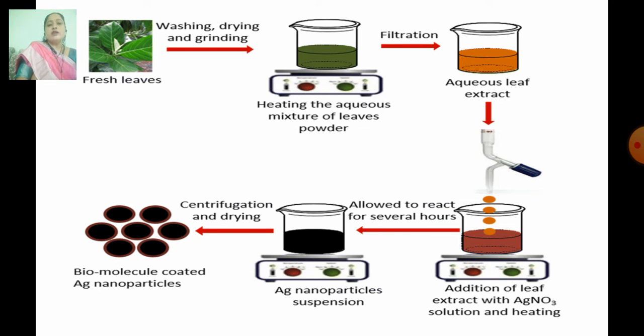After the formation of silver nanoparticles, you have to centrifuge it. After centrifugation and drying, we get biomolecule coated silver nanoparticles, and these silver nanoparticles have a number of applications in the medicinal field and have antibacterial properties. And therefore, like this, the jackfruit plant, also called Artocarpus heterophyllus, which everyone knows, we can extract in this way.